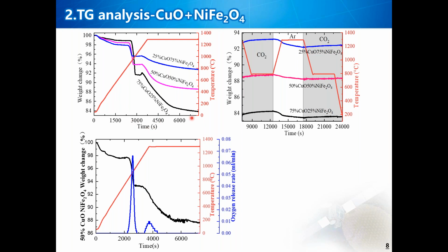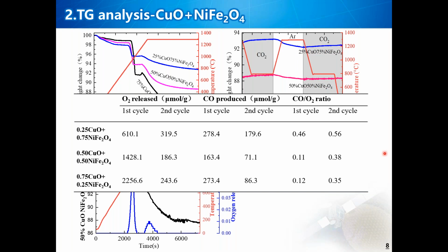The experimental conditions are the same as above. It can be seen that CuO has obviously oxygen released at 800 to 900 degrees, and the higher the nickel ferrite content, the lower the initial temperature of oxygen release. The oxygen release of nickel ferrite is mainly at 1100 to 1300 degrees. And by analyzing the experimental data, we can see that 25% CuO plus 75% nickel ferrite has the highest CO yield in two cycles and can achieve better stability.